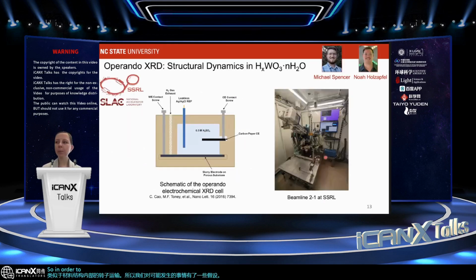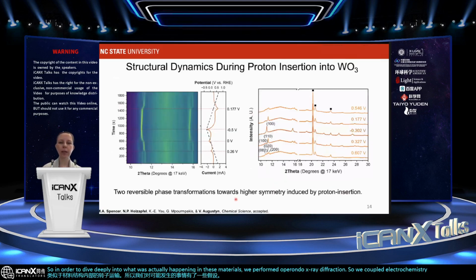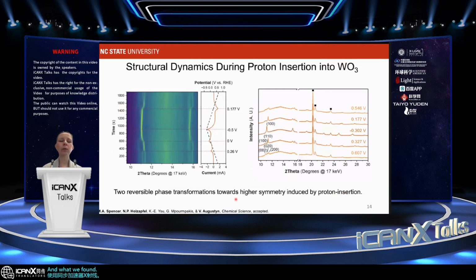So in order to dive deeply into what was actually happening in these materials, we performed operando X-ray diffraction. So we coupled electrochemistry with X-ray diffraction using synchrotron X-rays. And what we found was we were able to track the structural dynamics during proton insertion into those 3 tungsten oxide phases, the anhydrous one and then the 2 hydrated ones.